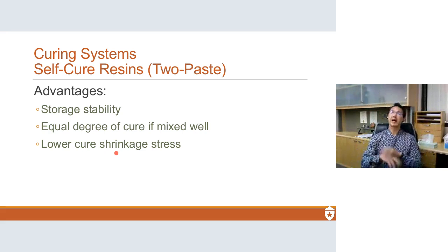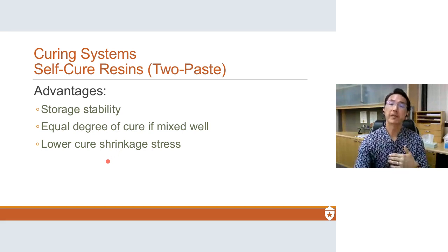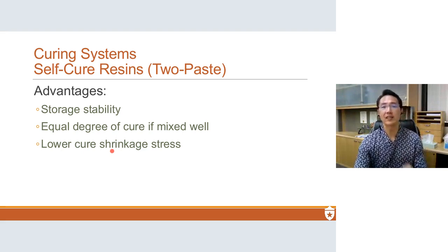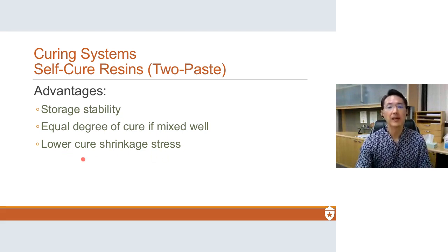I've been talking a lot about shrinkage, physical and volumetric shrinkage. However, the shrinkage itself, although part of it, is not the real reason for the marginal gap forming between the composite and the tooth structure as it shrinks. It's the stress that it generates as it shrinks. When that stress is large enough, it will create this gap. It'll pull away and break the bond. And so even if volumetrically something has the same shrinkage, if it generates less stress, and there are several ways that happens, it will not be as big a problem. Self-cure resins cure more slowly, so the stresses are able to be relieved as it cures, and it actually generates less shrinkage stress.